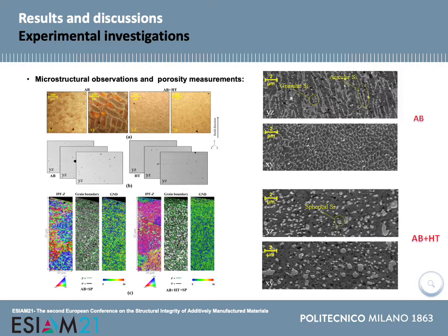In the EBSD analysis, shot peened samples in both as-built and heat-treated conditions were investigated. You can see, by considering the grain boundaries, high plastic deformation and high density of the grains in the top surface. Also, it can be observed that in the IPF, which shows the orientation of the samples, different orientations of the grains can be observed in the surface layer, which are placed randomly. In addition, GND, which is the factor of dislocation density, shows the highest value in the surface layer, like here and here, which confirms the highest rate of plastic deformation in the surface layer.